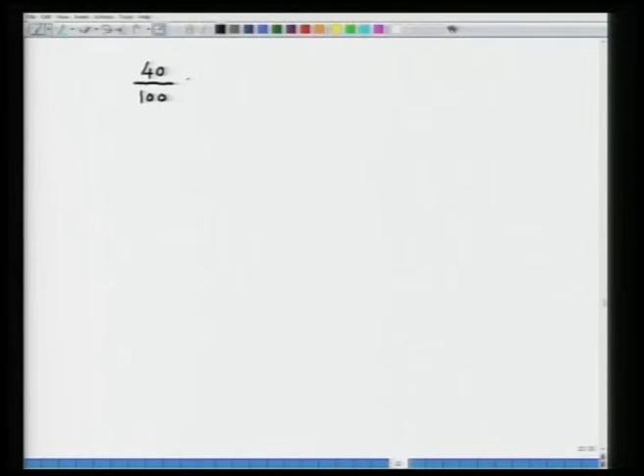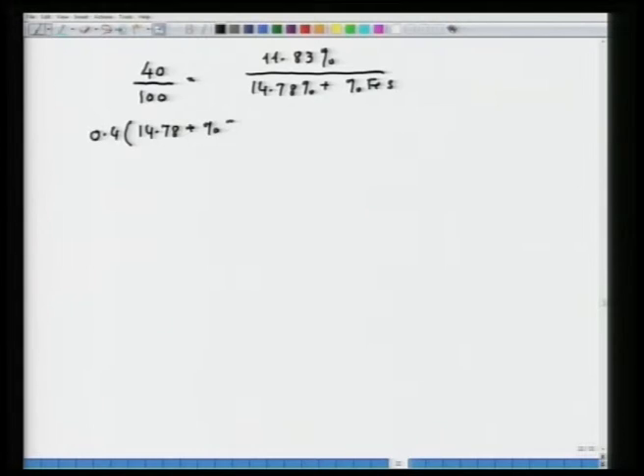We put the definition: 40 upon 100, that is the matte grade, is equal to 11.83% copper upon 14.78% plus percent FeS. So, if I solve this, I will get 0.4 into 14.78 plus percent FeS equal to 11.83. From here I get percent FeS, that will be 14.795. So, percent iron will be 9.415.